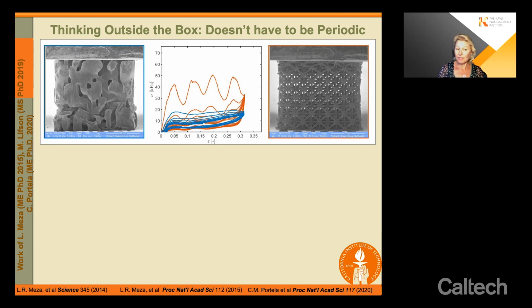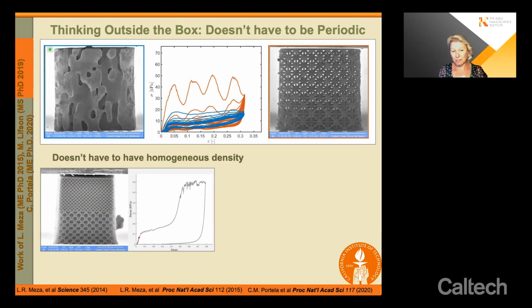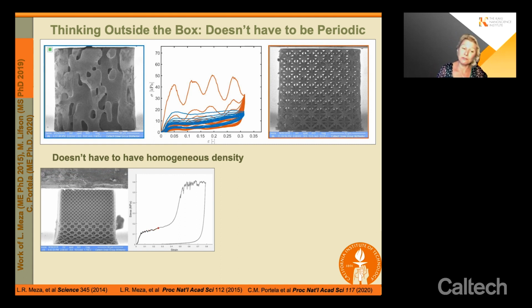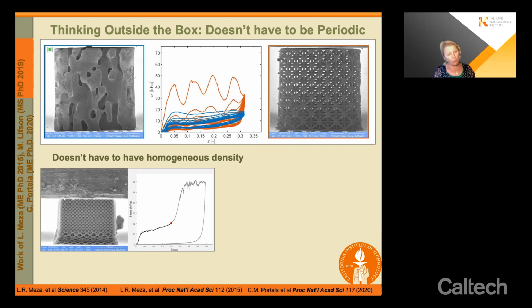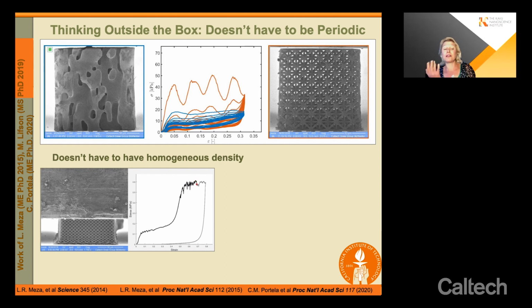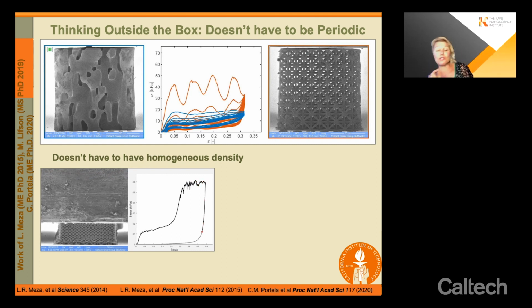What we've also learned is that these materials don't have to have homogeneous density. For example, when we're compressing something that has 2 distinct density regimes, this bottom part, which of course is more porous, so has a lower load-bearing capability, is fully compressing first and densifies first before the top part even knows that it's being compressed. So this allows us to pre-build the different trajectories of deformation and to elicit the specific response that we want.